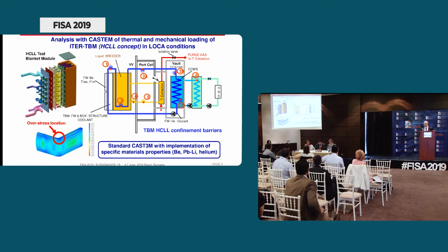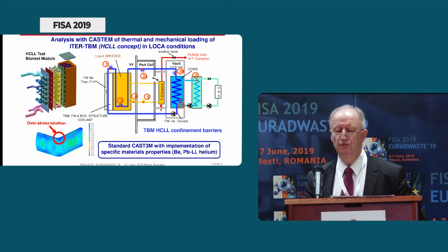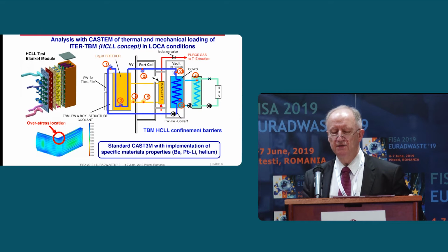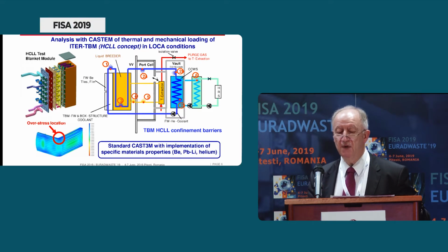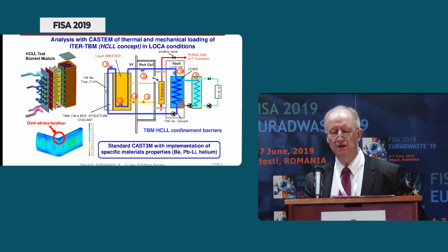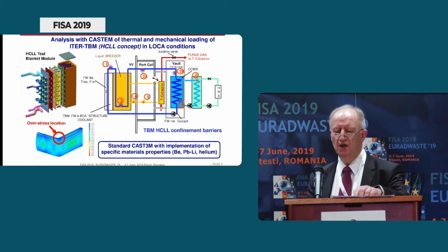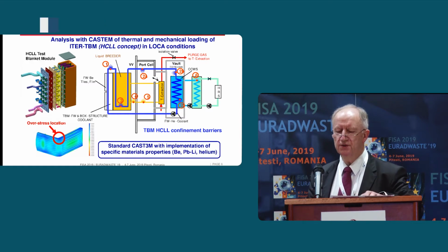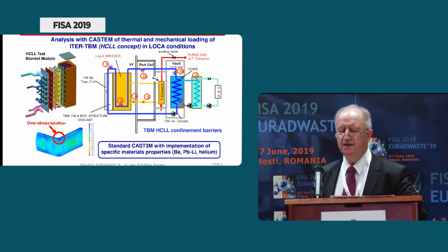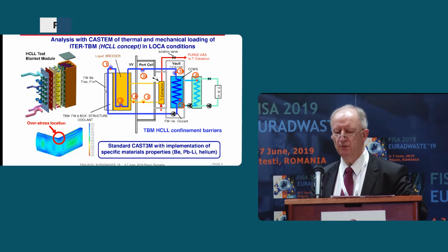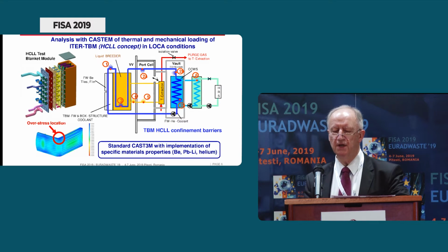Now, having a closer look at the design of the blanket and the first wall, this is a schematic of the cooling scheme. This is a helium-cooled lithium-lead blanket. Lithium-lead alloy is liquid above 237 degrees. You see that the helium first cools the first wall, which is the most heated part, then cools the front part of the blanket, then the back part of the blanket, which exchanges heat with water cooling. Then in a reactor, this water cooling would drive a turbine, and then there will be a heat sink at the end.